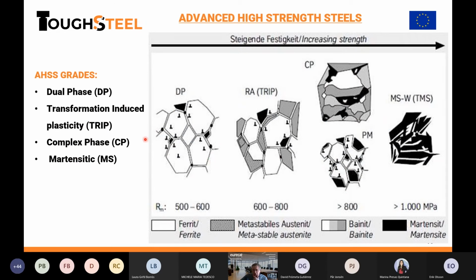Just some insight about the microstructure, because high-strength steels have many different microstructures that, of course, give at the end the properties for them. We have what is called dual phase. It's a combination of soft phase ferrite, hard phase martensite. Nice ductility because the formability is given by the ferrite, and high strength because of the martensite islands. If we increase the amount of high resistant phases, I mean martensite or bainite, we can have the TRIP steels with some retained austenite. Remember that TRIP steels have the ability to produce induced plasticity during the deformation, because of the transformation of retained austenite to martensite that hardens the material during deformation. This is expected to have high formability associated with high strength.